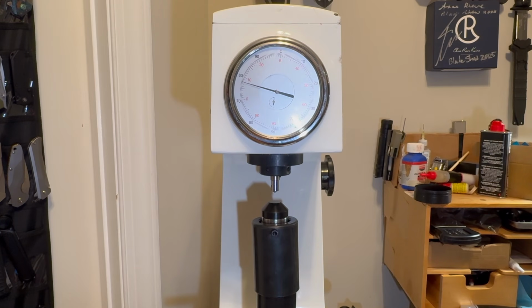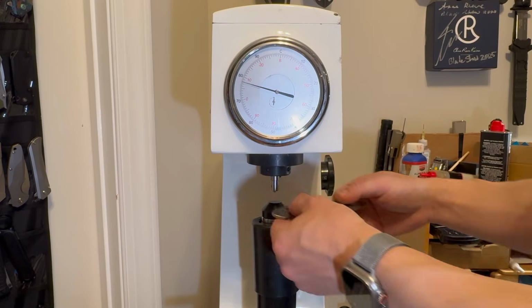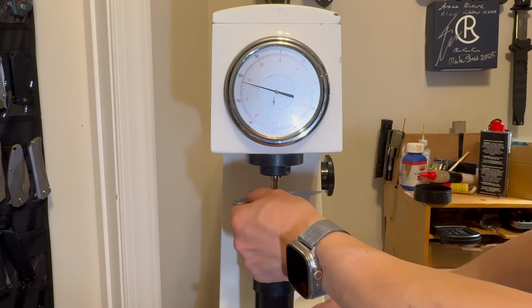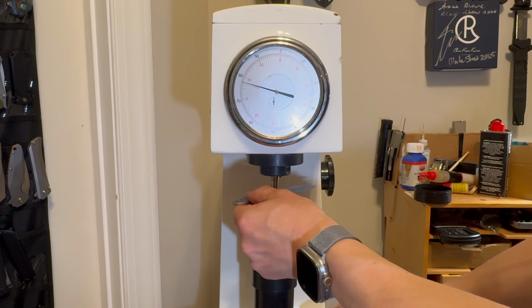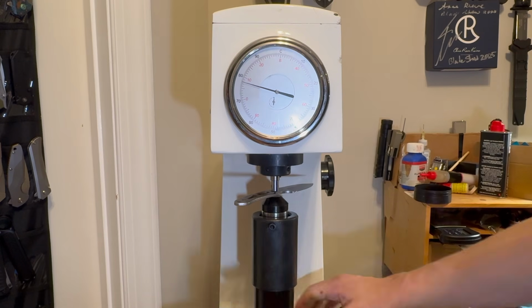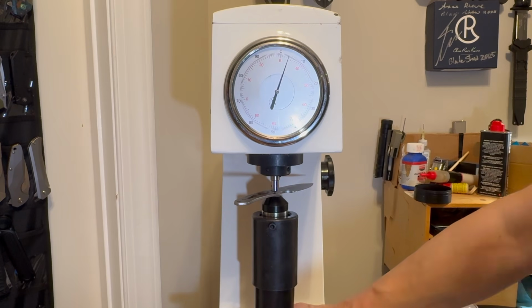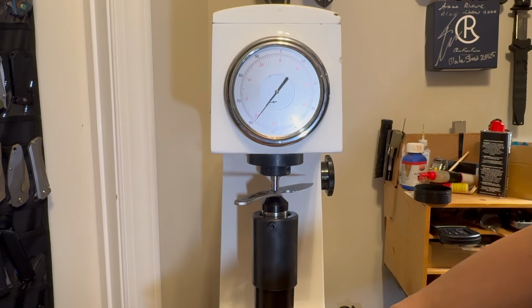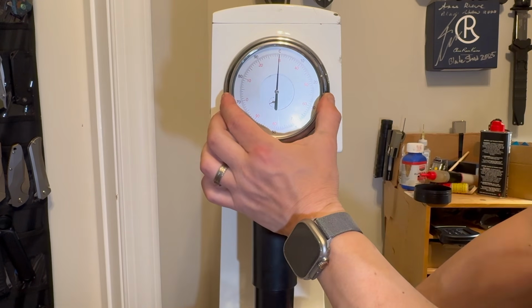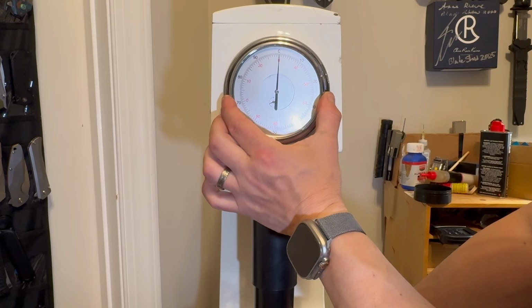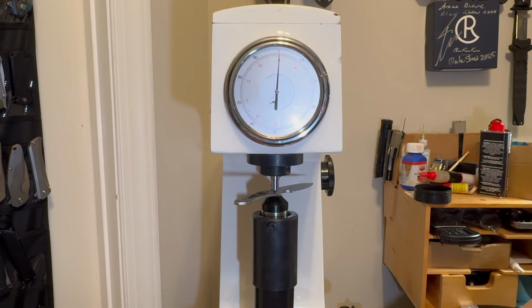And so let's start the test with the older version of 632. If you skip through some parts of the video, this is my older Alpha Scout, which is uncoated. The question we're trying to answer today is: is Buck pre-planning Cerakoting by heat treating the uncoated blades slightly higher than their typical 57.5 to 58.5 HRC? Having measured several Buck uncoated blades previously, that's where all their fixed blades come in. At this budget level of pricing, I have my doubts, and we'll find out here in a second.